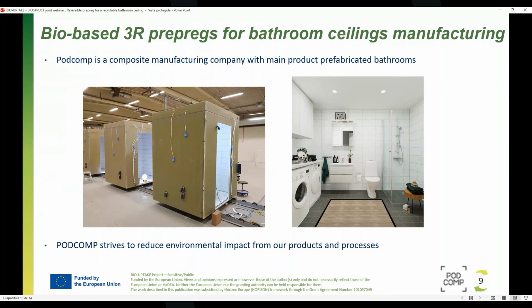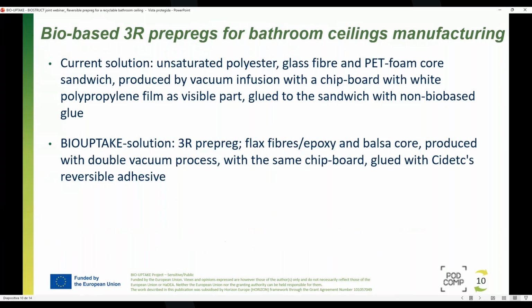Okay, next slide. So the current solution is made from unsaturated polyester, glass fiber, and a PET foam core sandwich. That is what the whole bathroom is built from, floor, walls, and ceiling. And the panels are produced by vacuum infusion. They have a chipboard with a white polypropylene film as the visible part inside the bathroom, and it's glued to the sandwich with a non-bio-based glue.